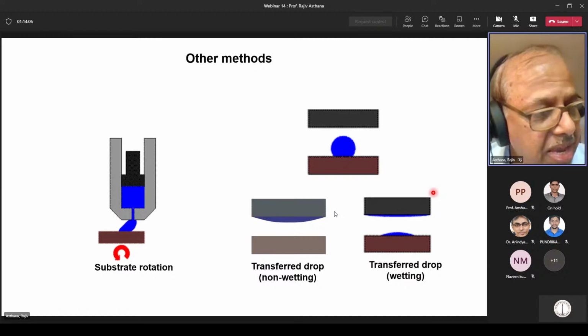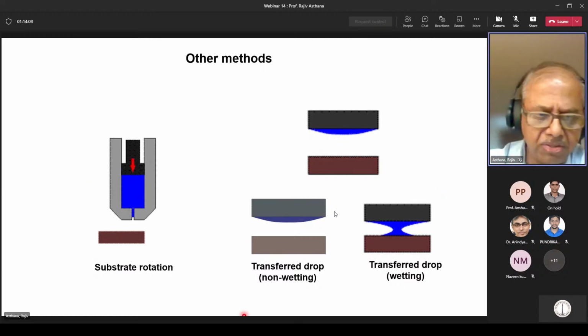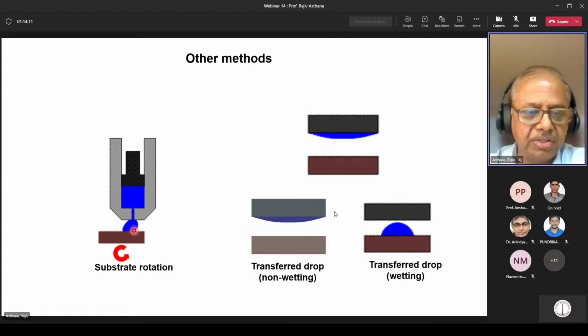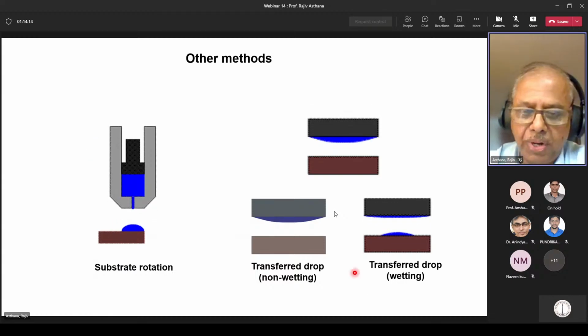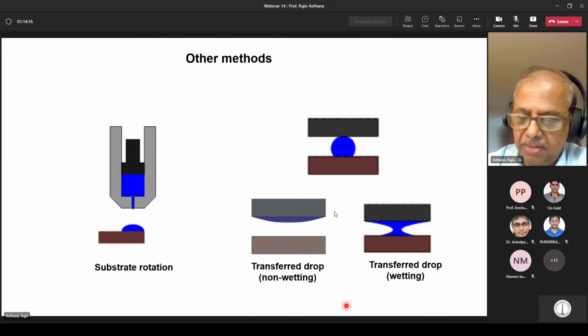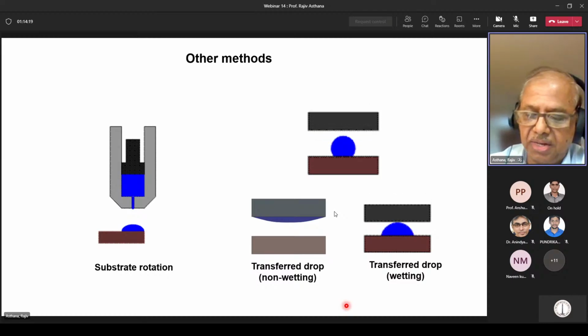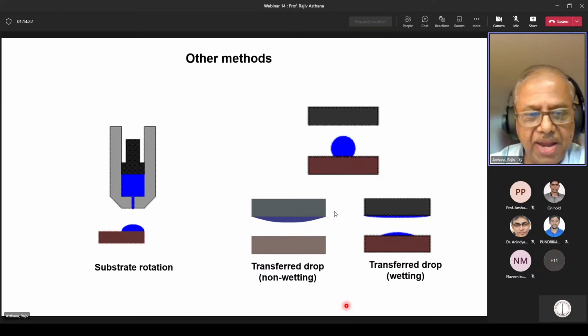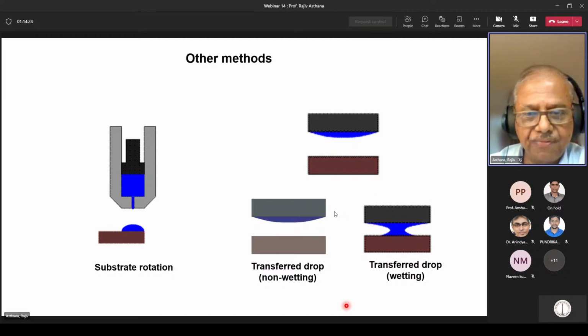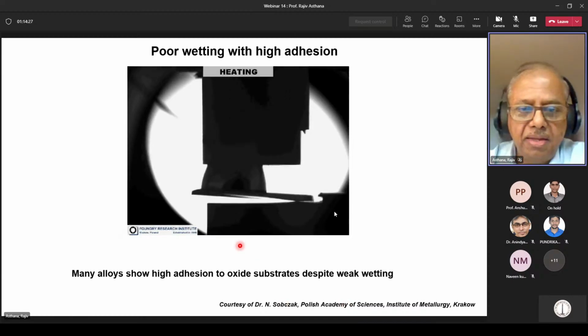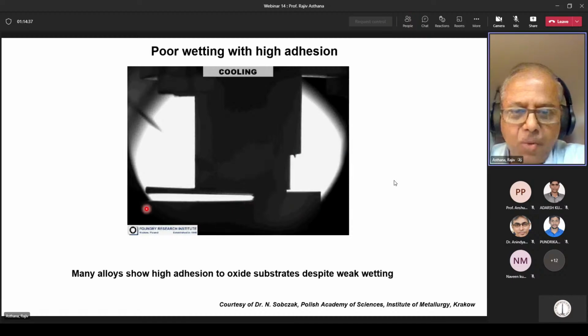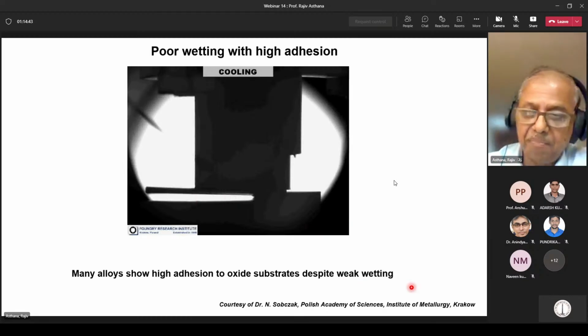Several other types of tests can be done. I will not spend time showing these, but you can actually shear the droplet during the squeezing process, and that allows you to study how clean, oxide-free liquid will contact a moving surface. Here you're looking at a system where the wetting, the contact angle, was poor, but again, the adhesion is good. So this ceramic is actually lifted up when the liquid solidifies because the contact was very good.